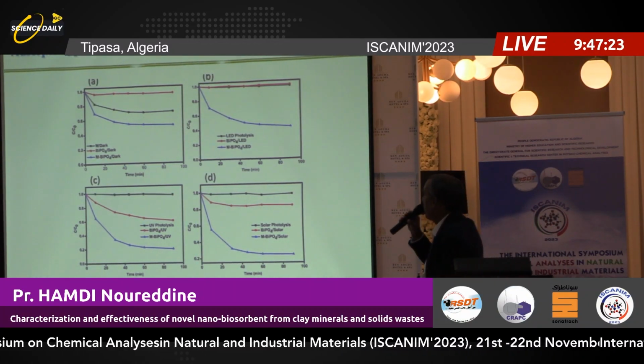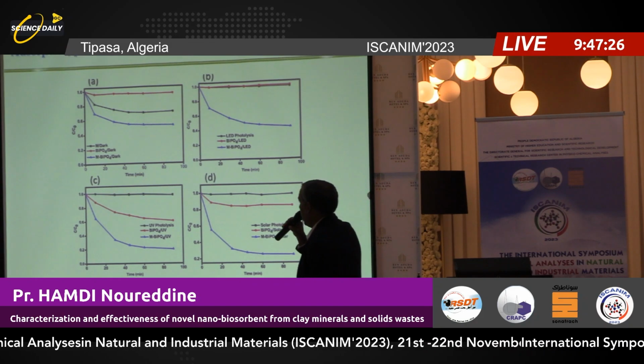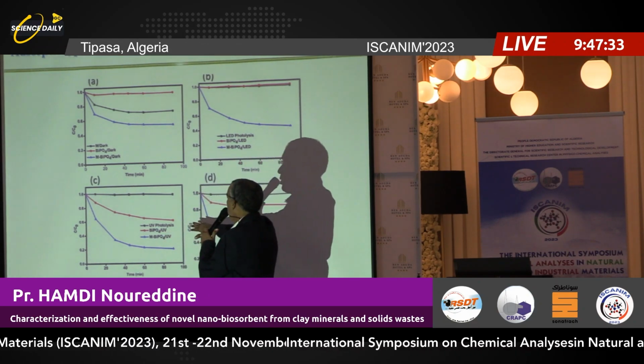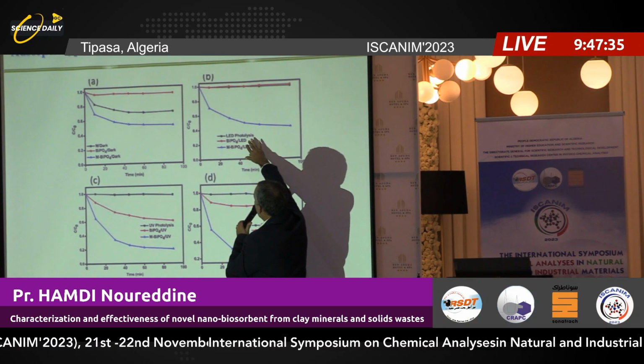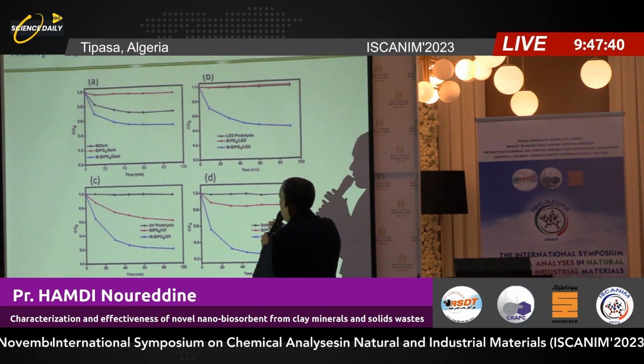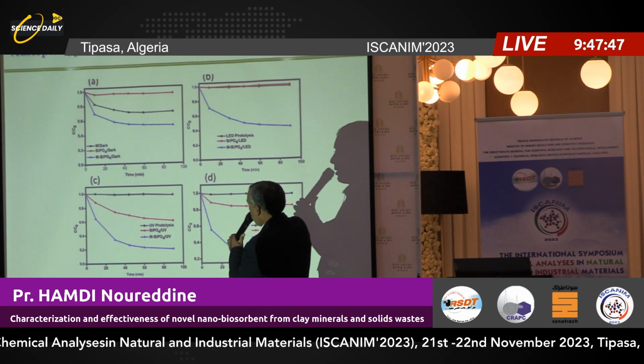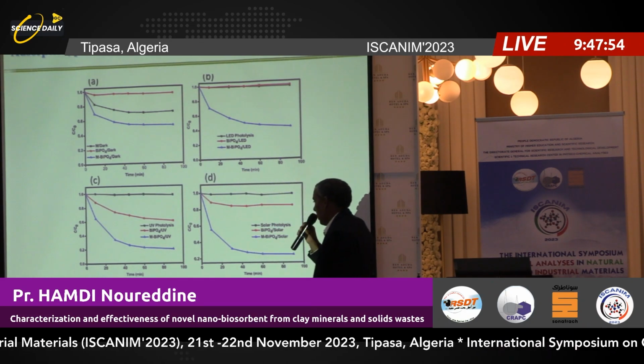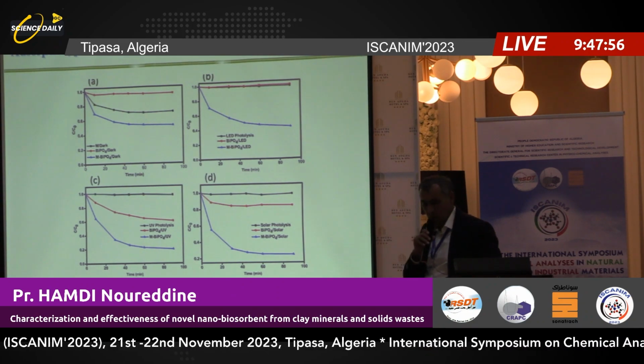Now the photocatalysis and adsorption are combined: firstly in the dark, after that in UV photolysis and LED photolysis, and after that in solar light photolysis. You can find that in both cases, UV and solar, the adsorption and photocatalysis are very high, and the ratio C over C0 is about 0.1.